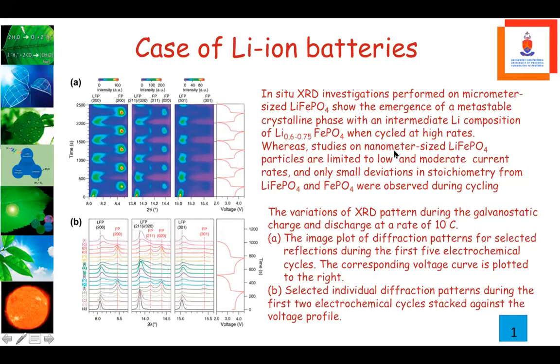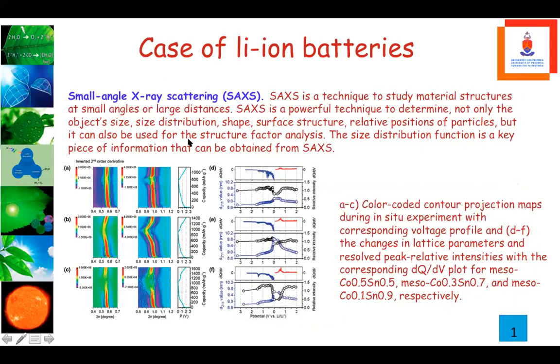Whereas studies on nanometer scaled lithium iron phosphate particles are limited to low and moderate current rates, only deviations in stoichiometry from these two were observed during the experiment. The results that you see on the left show the variation. The picture here shows...